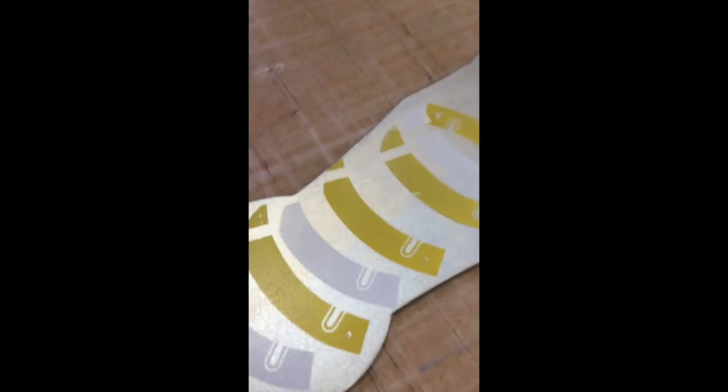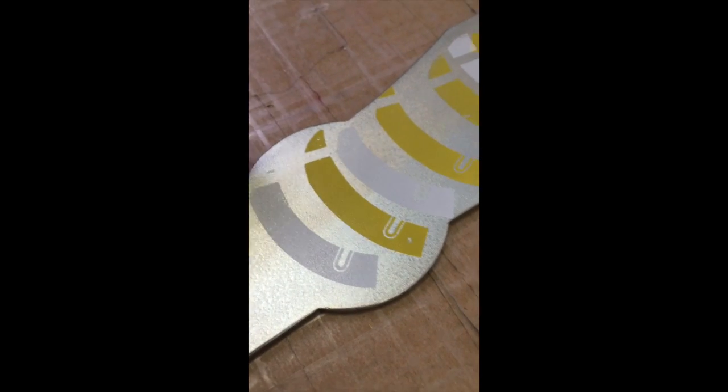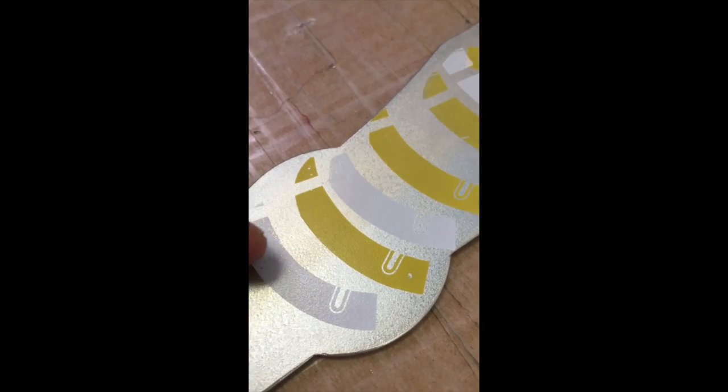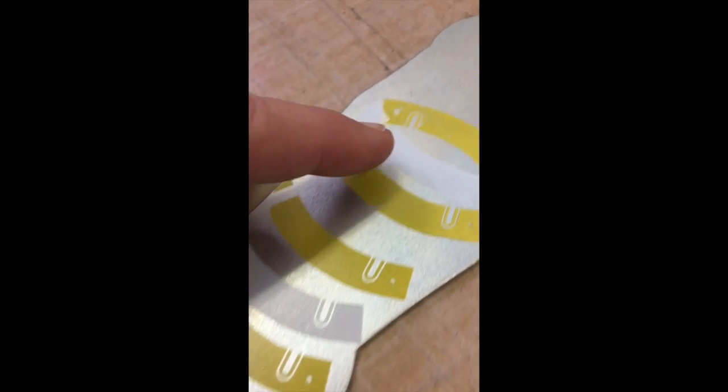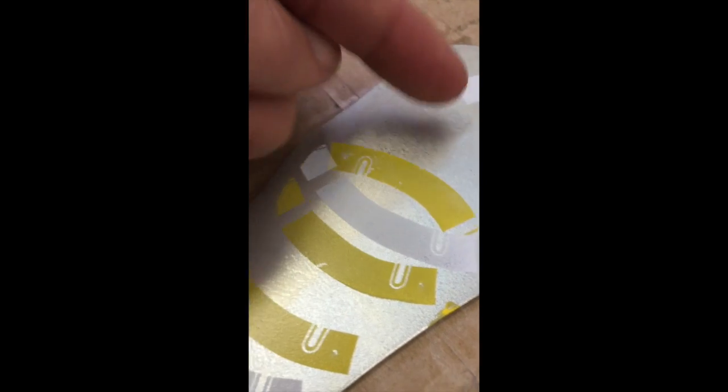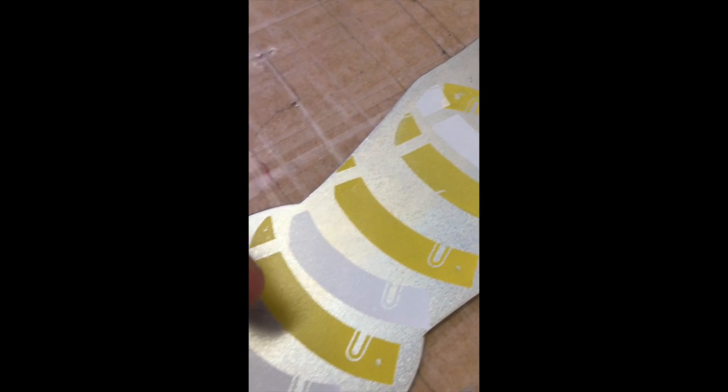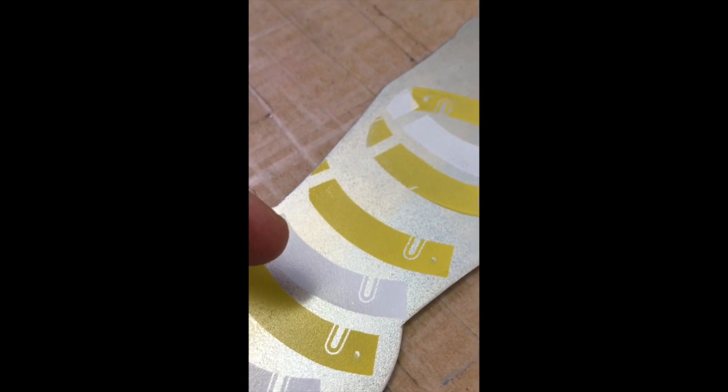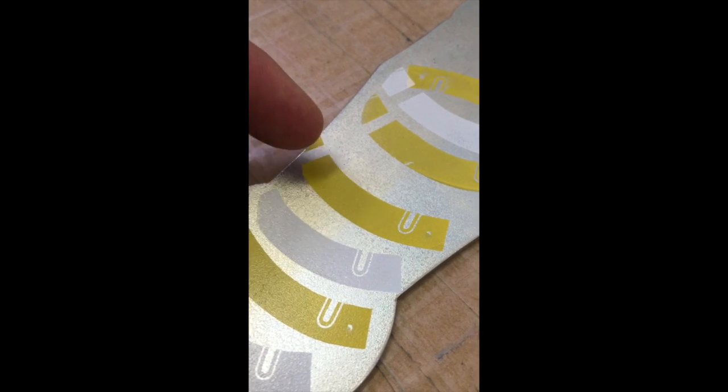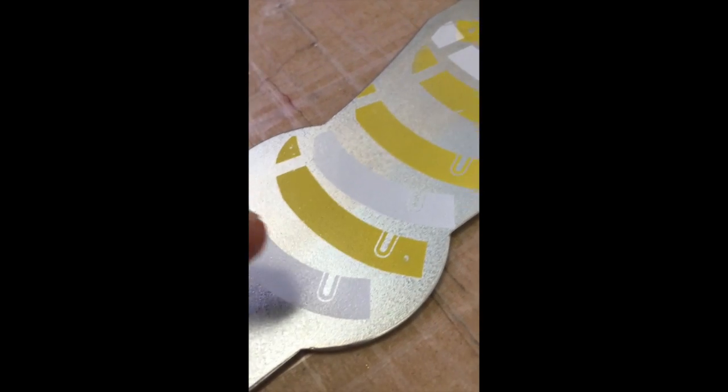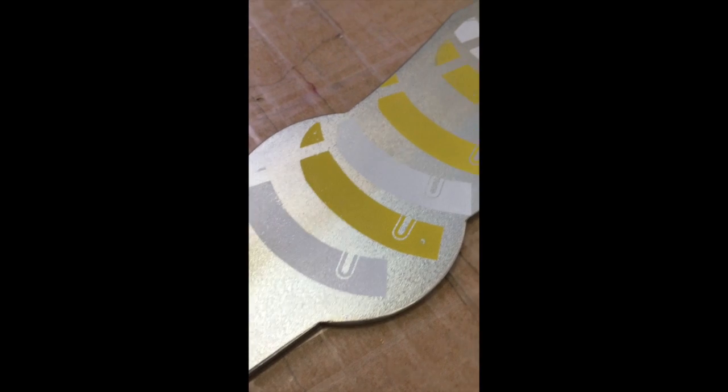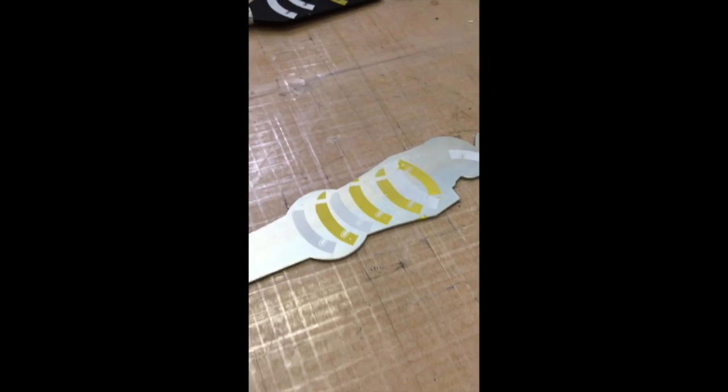And we definitely lost, had pulled some ink off. And if we look down now at the part, you can see the failures along the top here. This is the side that hasn't been cleaned. You can see that there's definitely failure on this side and not on the other side. So there we go then. It looks like the answer to the question is clean the parts.